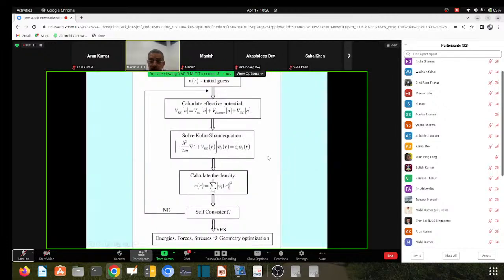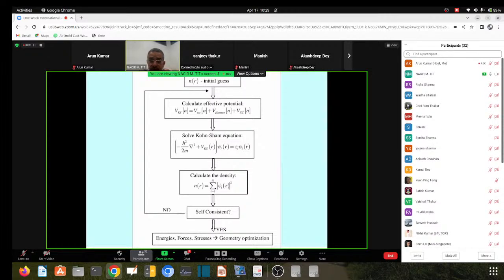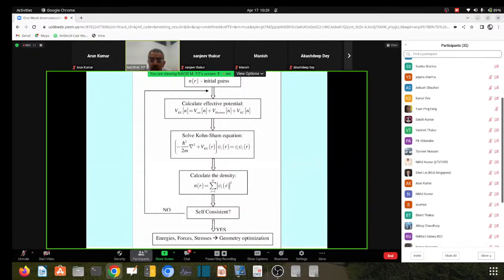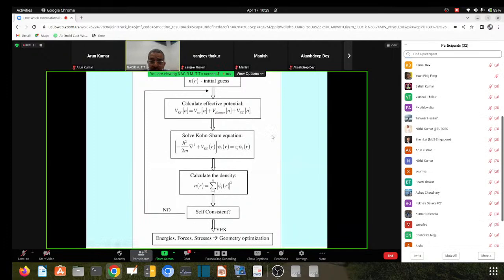So now, regarding DFT, as I said, we start with an initial guess of the charge density, and we start iterating. How do we calculate the effective potential? It consists of the external potential, which is like a pseudopotential, the interaction of the electron with the ions, plus the Hartree term, which is the interaction of a single electron with the remaining electrons, like density. So there is a Hartree term there, which is very possible to converge, plus the exchange correlation potential. So we make the Schrodinger equation.